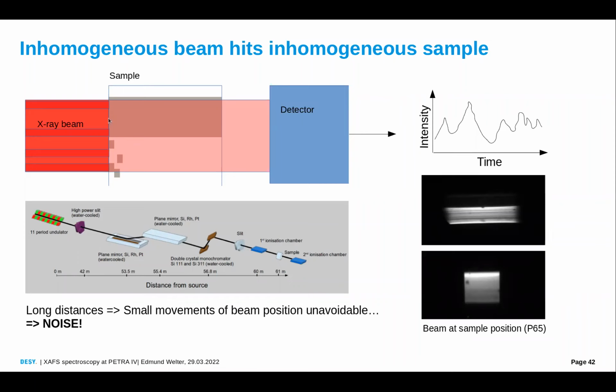And what's happening is the typical XAFS sample is not ideal, doesn't have ideal homogeneity. So if the beam is moving a bit, we are probing the inhomogeneities of the sample and not so much the XAFS, and we get a lot of additional noise. So that's a bad situation, and one would rather use an incoherent source or source with lower degree of coherence to do the XAFS experiment.